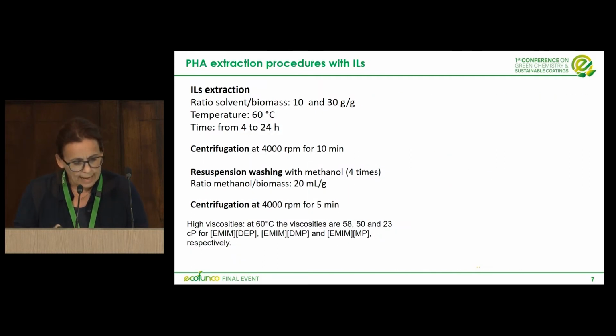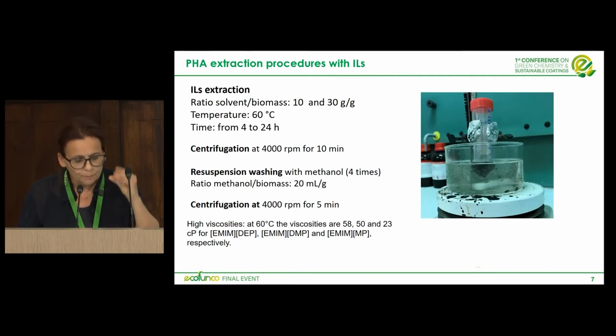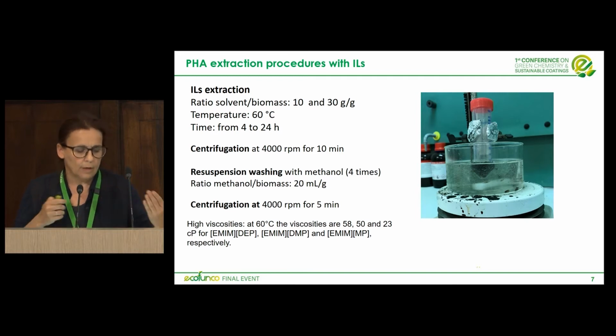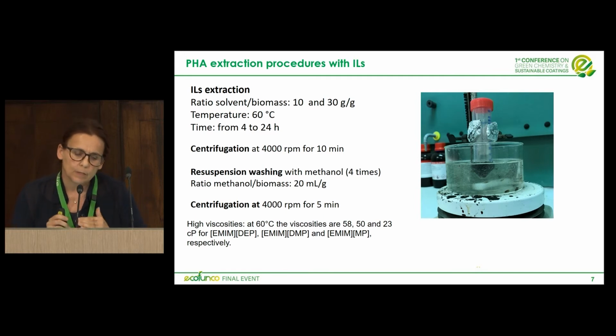So, in the case of the ionic liquid extraction, we have used this ratio solvent to biomass at a temperature of 60 degrees for 4 to 24 hours. In this case, we have a solvent with very high viscosities. In fact, you can see that at 60 degrees, we have very high viscosity of the ionic liquids: 58, 50, and 23 centipoise. I remind you that the viscosity of water at room temperature is just 1 centipoise. Consequently, we have very high viscosity.